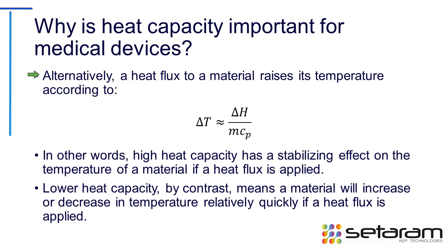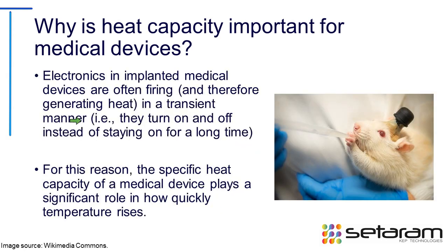When we look at what it's important for in biological systems, it's in the case of heat fluxes. So in the case of brain probes, where we're applying a heat flux due to electrically implanted devices, we have a quick transient heat source, which is going to cause some type of temperature rise in the implant or in the electronic devices. So in other words, according to this formula right here, the change in temperature is inversely proportional to the heat capacity of the material. So high heat capacity has more of a stabilizing effect on the temperature change. So in the case of water, we have a more stabilizing effect of the temperature change. It's very difficult for it to occur. But in the case of metals, in implanted devices, a very fast change in a heat flux will have a dramatic increase in temperature. And we can tune this by changing some of the thermal properties of the heat capacity itself. So that's exactly what I just explained.